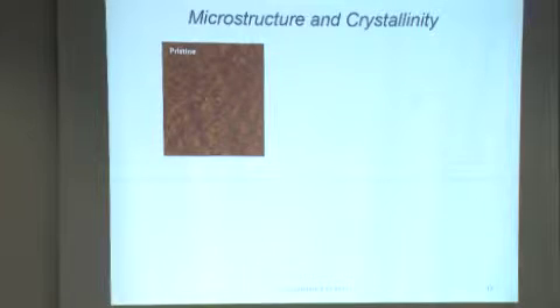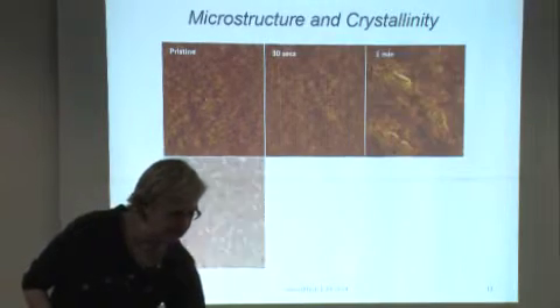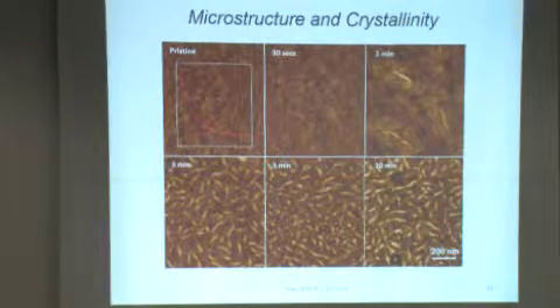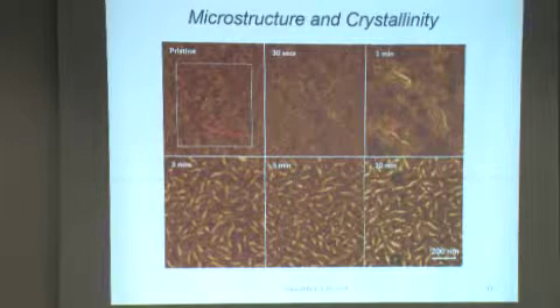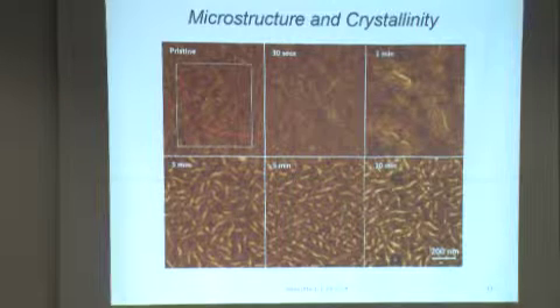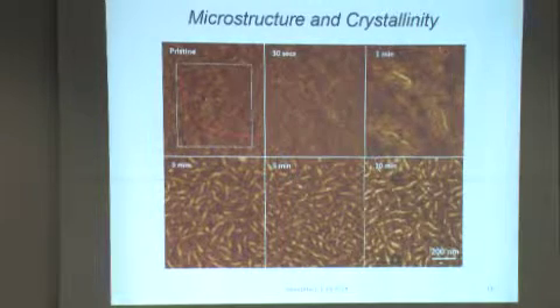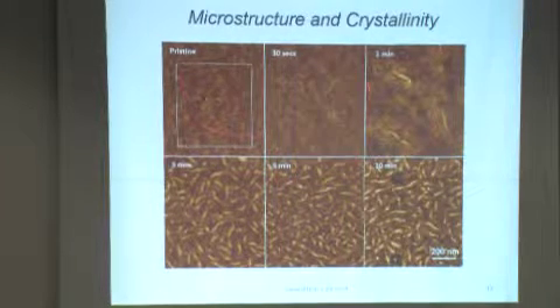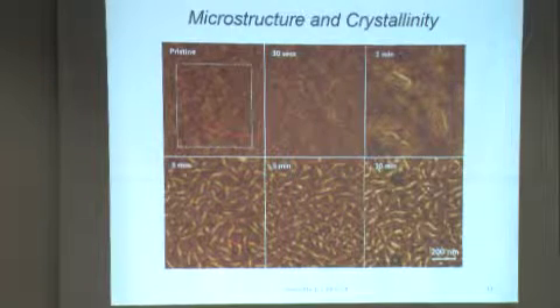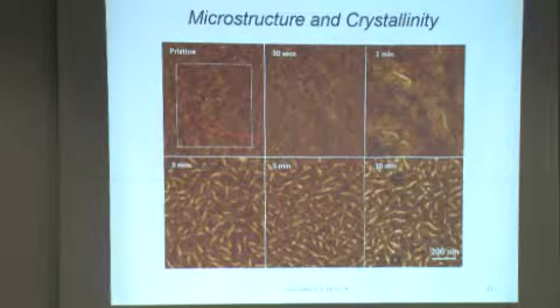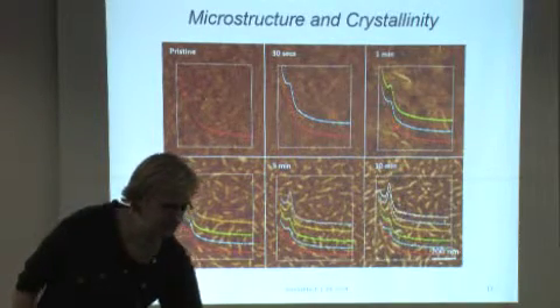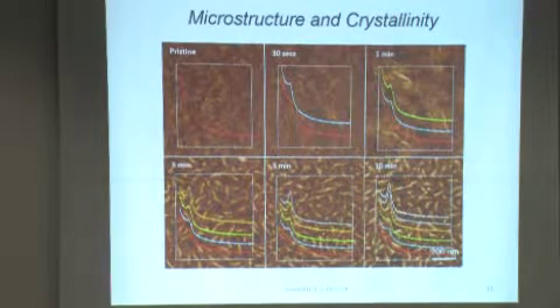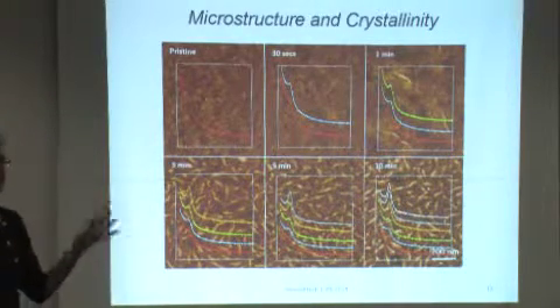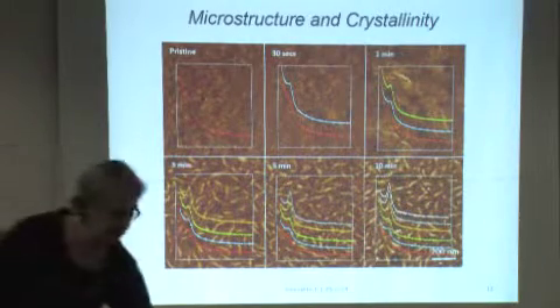All right, so the pristine material looks kind of amorphous. As we continue to sonicate the solution and then deposit thin films from 30 seconds up to 10 minutes, we start to see what looks like some sort of crystallite-like features forming. And as you sonicate further, you tend to get more of these. Looking at the X-ray diffraction patterns, we see an enhancement in crystallinity of those films as we sonicate more. So we naively figured that better crystallinity would obviously have to mean better mobility. Well, that wasn't really the case.